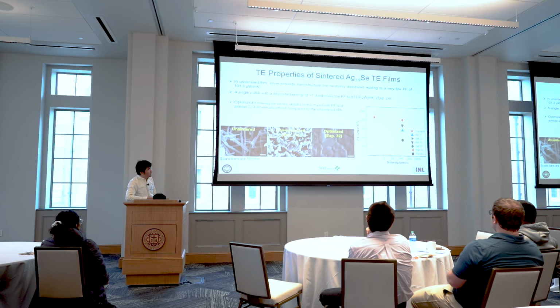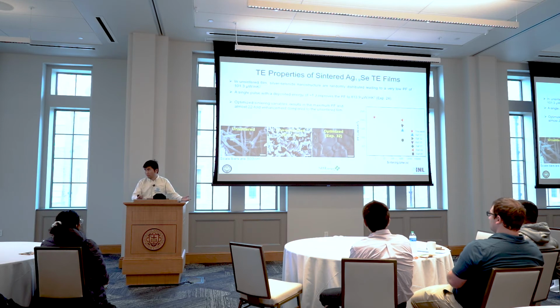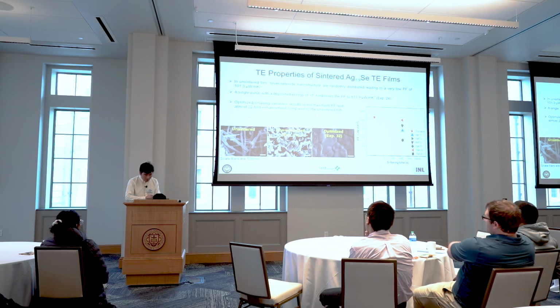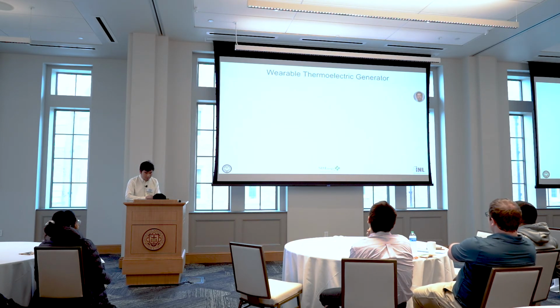And then if we put our power factor in perspective with respect to other work, as you can see, our power factor is higher than the best. And also, these people use oven sintering, which takes hours. We take a few seconds. Okay? So this is a big success from our point of view.